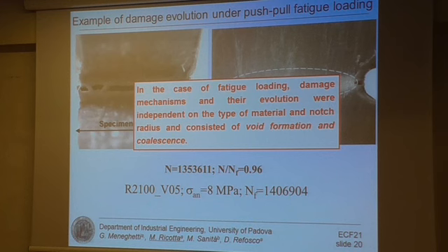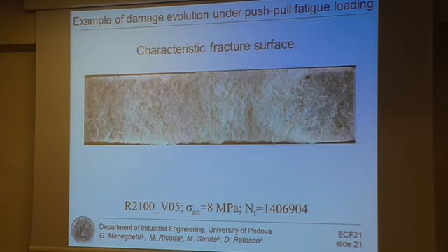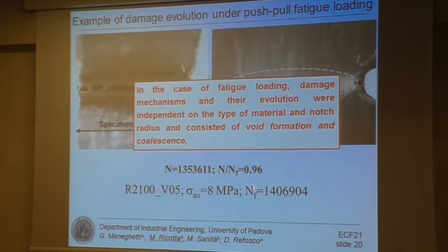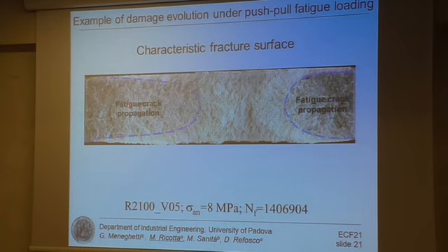This type of analysis was carried out for all the compounds and the notch geometries investigated in this paper, and we can conclude that in the case of fatigue loading, the damage mechanisms and their evolution were independent of the type of material and notch radius. As in the case of static load, this mechanism consisted of void formation and coalescence. Just an example of a characteristic fracture surface. This is the fracture surface of the same specimens. And we can see here the gray zone where the crack propagated from both the notches, and the white zone is where the static failure happens at the end of the fatigue test.